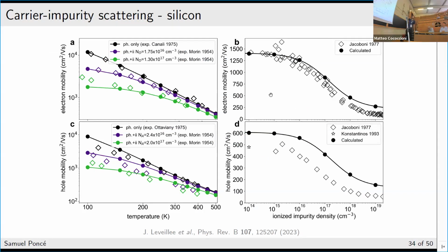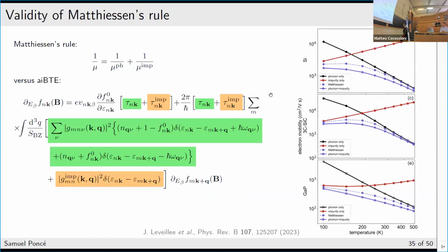And as you can see, this is the result with only phonon. So this is what we showed before compared to experiment. But now if I'm increasing the amount of charge, so 10 to the 16, 10 to the 17 dopant, then what is happening is that the mobility is decreasing, which you expect because you are putting in more scattering. So this is at room temperature. You can see that here I'm in this intrinsic limit, which is flat. And then basically I'm reducing the mobility due to this additional scattering, and we can do that as a function of temperature or as a function of ionized impurity density.